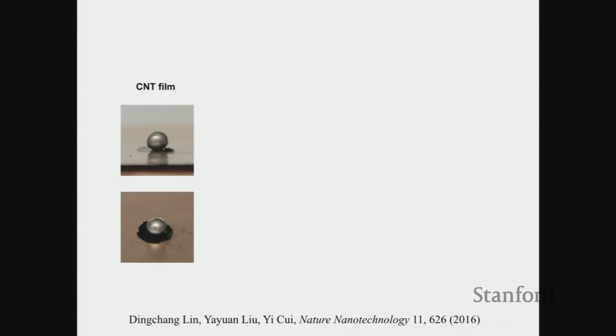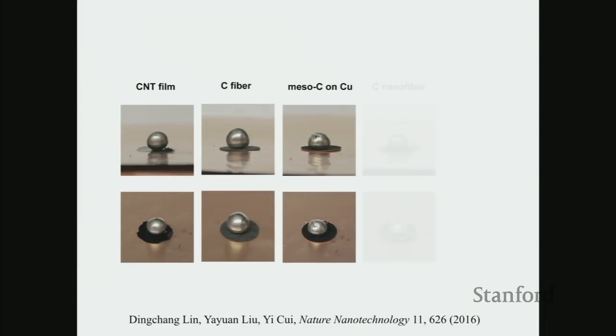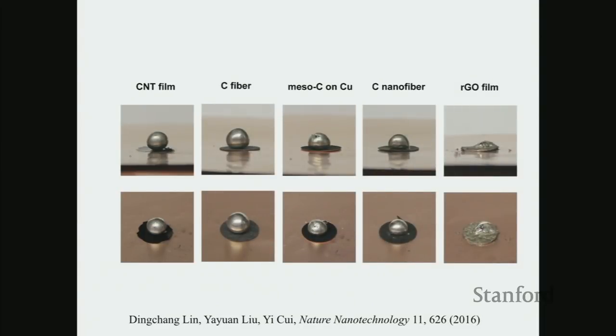So we wanted to use metallic lithium in the molten state, melt the lithium, and embed it into a host. We searched carbon nanotube film as the host. You see this molten lithium forms droplets; they don't wet. We tried all types of substrate until we tried the reduced graphene oxide. Now you see the lithium melts, wets, and goes into the structure right away.